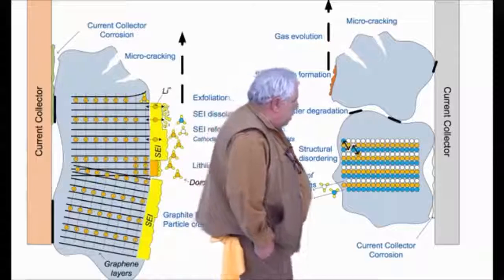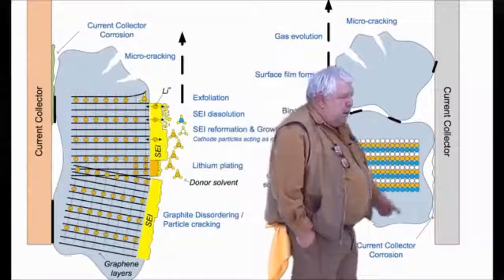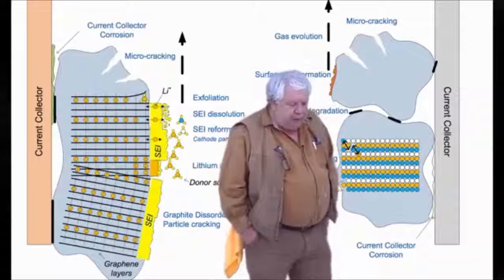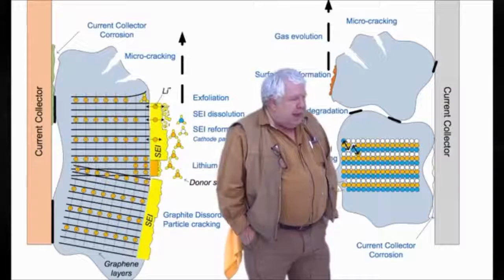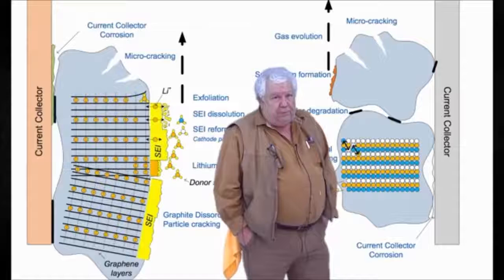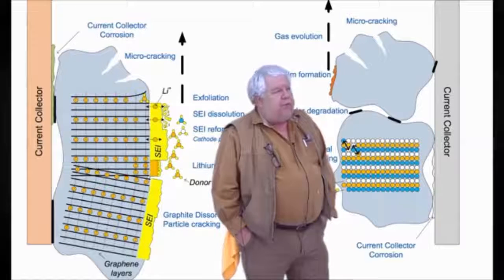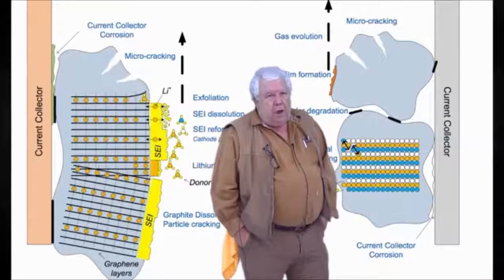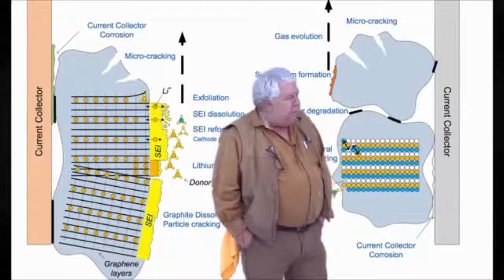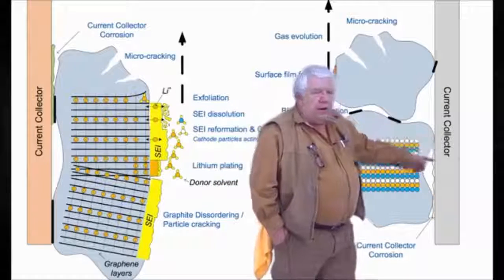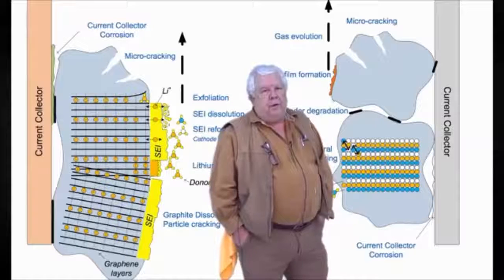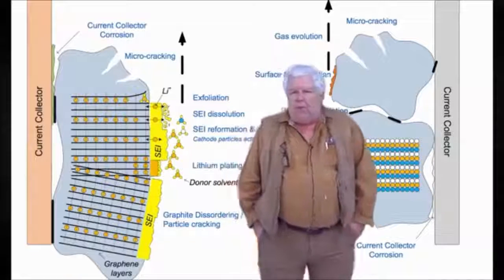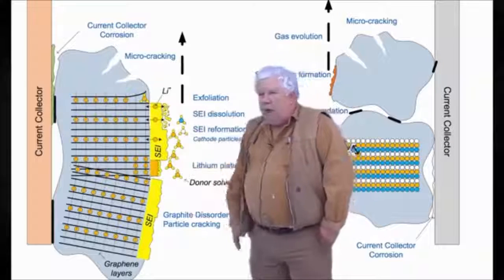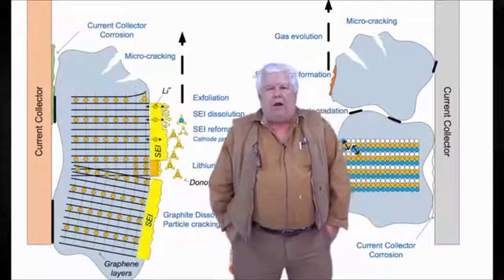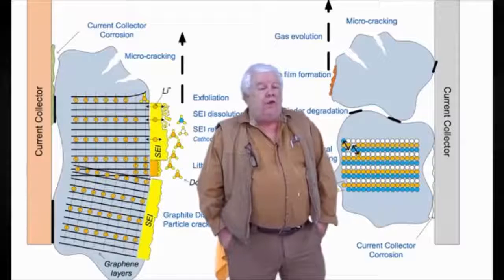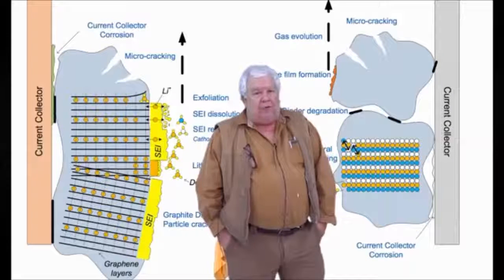Over here on the cathode, we have some iron remaining, some phosphorus, and some oxygen. At about 250 degrees centigrade, up to about 400, this starts to break down and release free oxygen. Now, free oxygen can combine with the electrolytes and with the lithium ions, and we have a fire burning out of control that you can't put out because it makes its own oxygen.